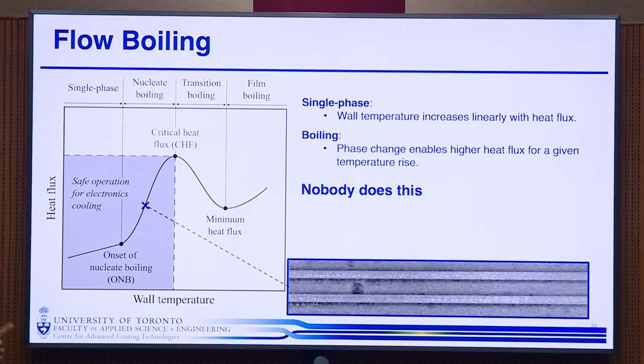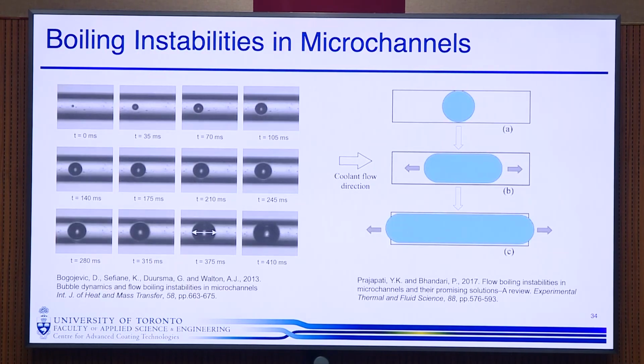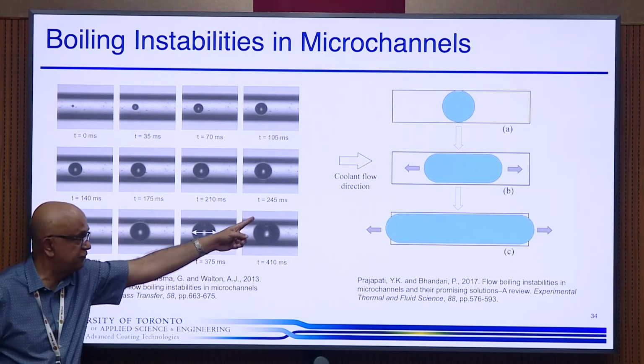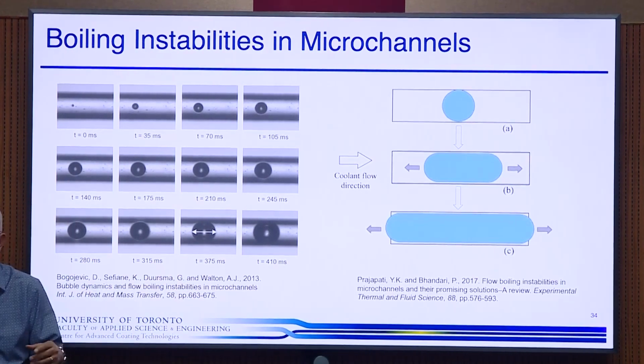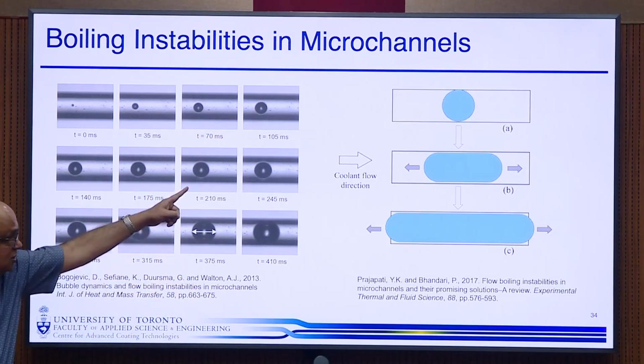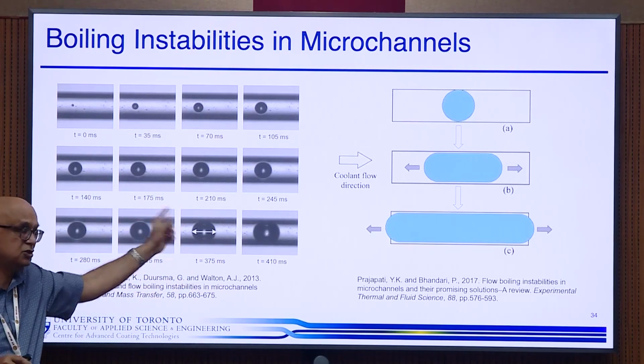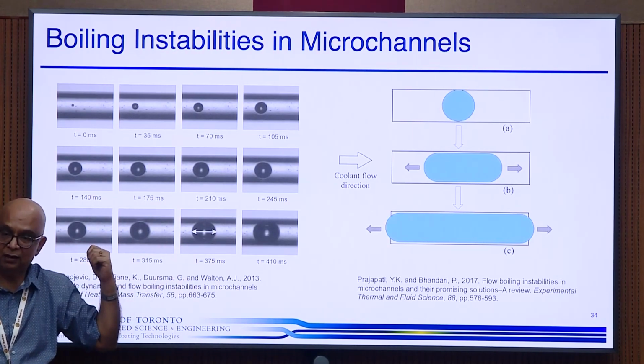The thing is, nobody does this, right? So commercially, nobody's got over there. And the reason simply is because of the instabilities. So what happens is that if you start getting boiling inside your microchannel, you get a bubble, and the bubble grows very rapidly, and it fills the entire microchannel. Now it doesn't have any place to grow, so it starts growing in both directions along the length, and it actually starts pushing the liquid back.